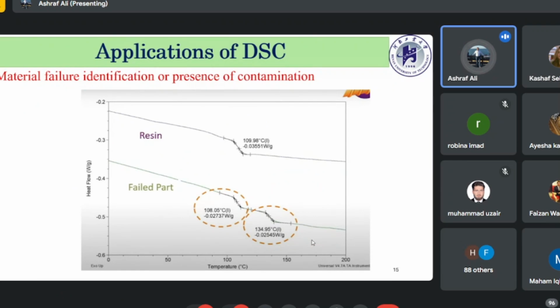Similarly, we can also find out whether this material has some failure or not, or whether this material has some contamination or not. The first curve shows the DSC analysis of a pure resin or a pure polymer material, and you can see that here the melting temperature is about 109.98 degrees C. But if you look at the second curve, this material contains some impurities, so it has shown us two different melting temperatures, and these two different convolutions in this curve show that this material is not 100% pure and it contains some contamination.